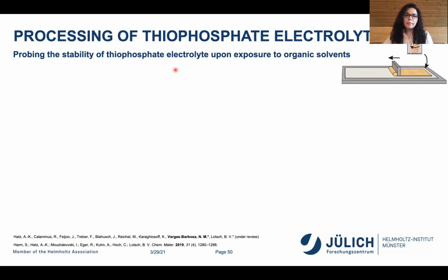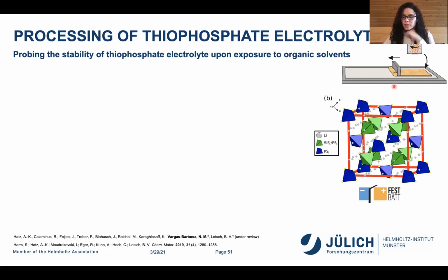One of the processes that we're trying to study is how to make thin films. So taking the thiophosphates and exposing them to some sort of organic solvent and using that to cast a slurry-based thin film of the solid electrolyte. This was done again in collaboration with the Lotsch Group and supported by the FestBatt consortium.